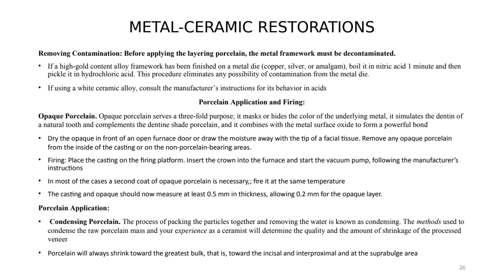Dry the opaque in front of an open furnace door or remove the moisture with the tip of a facial tissue. Remove any opaque porcelain from the inside of the casting or the non-porcelain bearing areas. Firing: place the casting on the firing platform, insert the crown into the furnace, and start the vacuum pump following the manufacturer instruction. In most cases, a second coat of opaque porcelain is necessary, fired at the same temperature. The casting and opaque should now measure at least 0.5 mm in thickness, allowing 0.2 mm for the opaque layer.